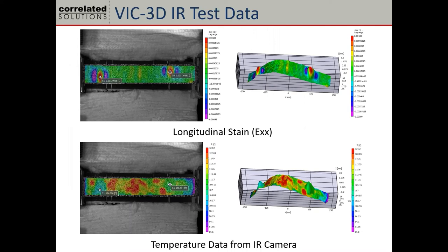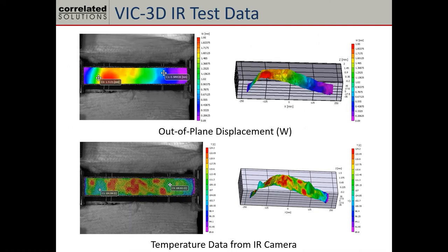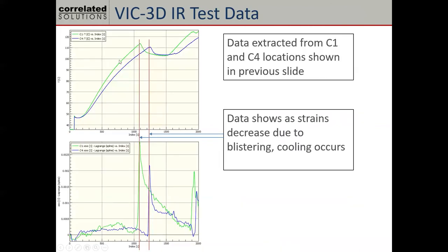Results from the IR-DIC integration show simultaneous longitudinal strain and temperature fields. During compression and thermal loading, you can see the specimen buckle, with strain concentration where it delaminates and corresponding temperature changes around those areas. This technique enables measurement of local coefficient of thermal expansion at different regions, warpage measurement, and is commonly applied to computer chips and CPUs. It provides a comprehensive dataset linking mechanical deformation to thermal behavior.